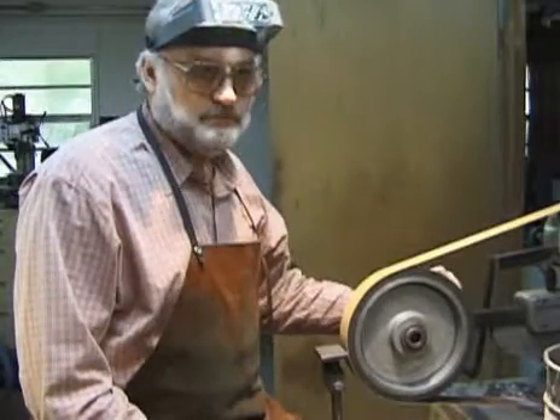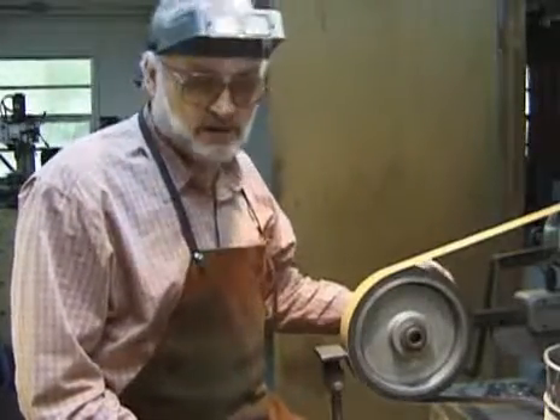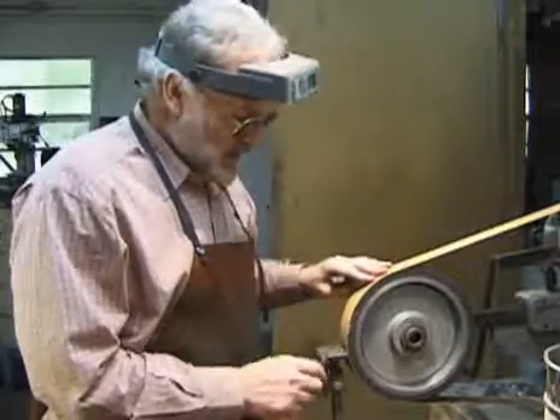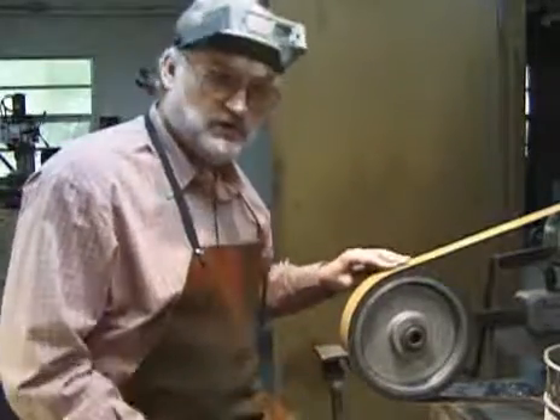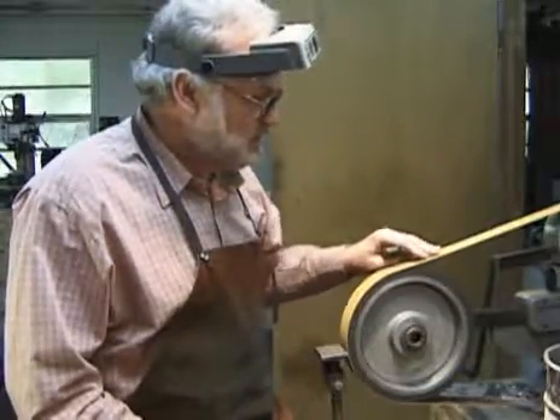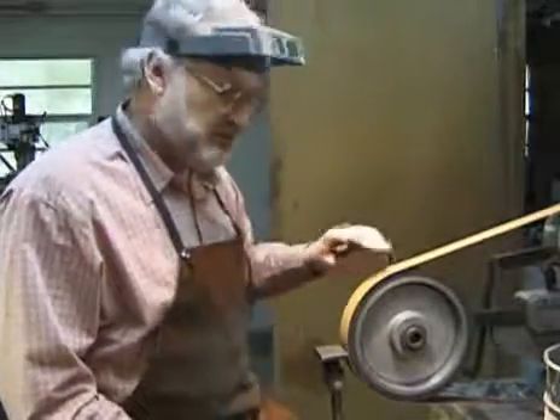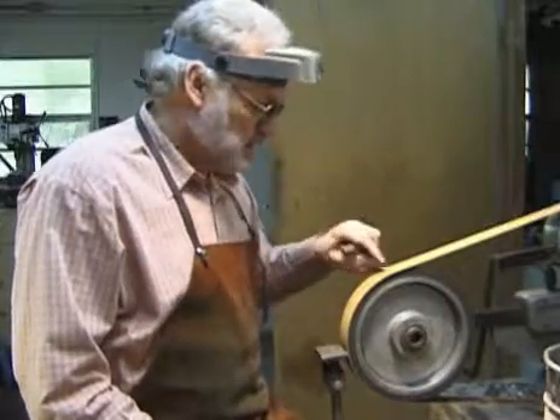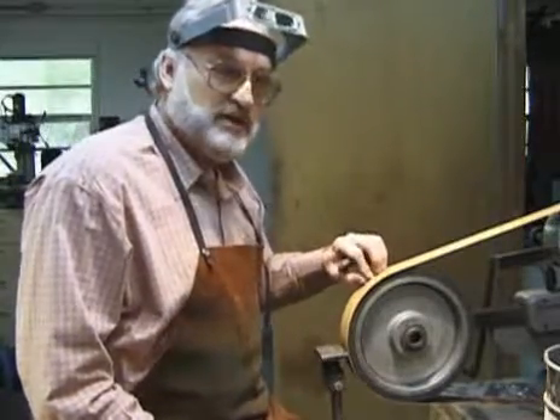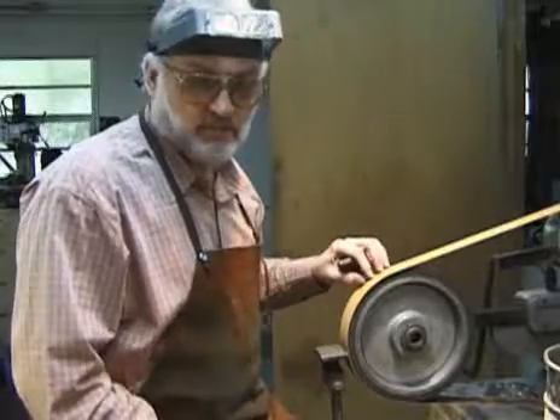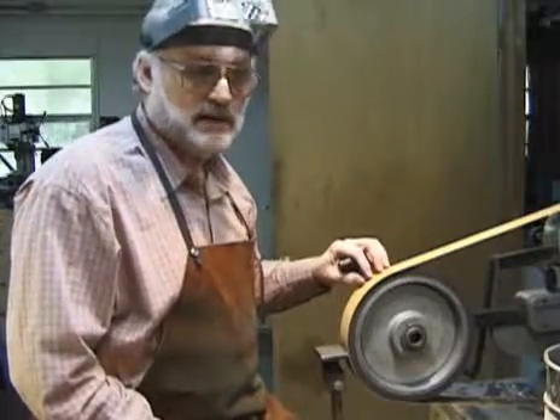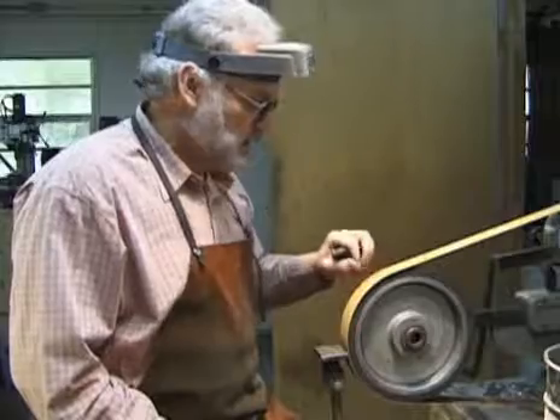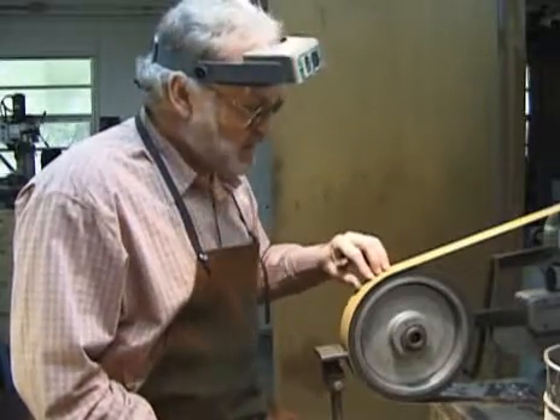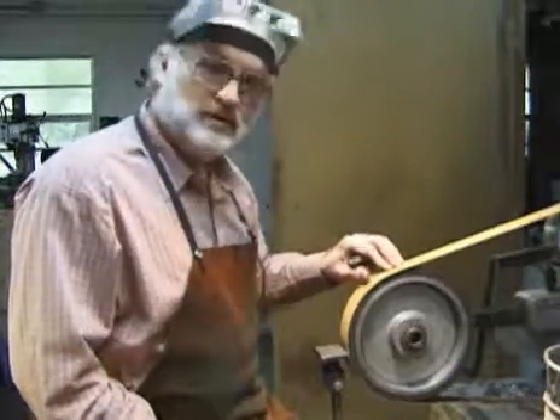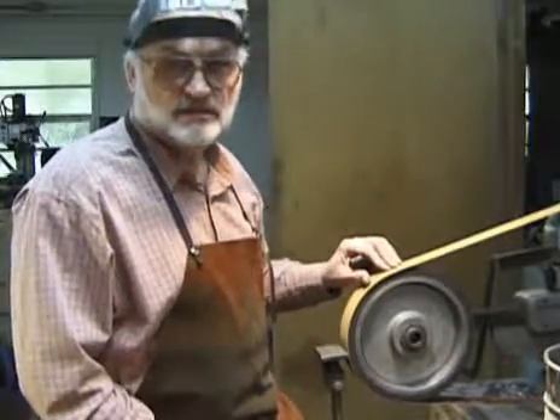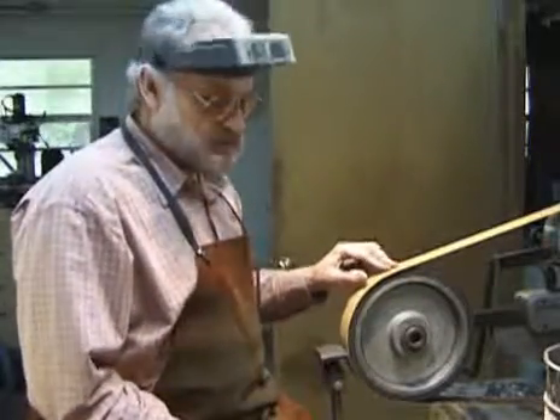When you're getting into your finished grinds on your blades, I'm using a coarse grit here. This is a 60 grit. Actually, it's an 80. No, it's a 60 grit ceramic belt. The benefit of the ceramic, it cuts very, very deep because the grit is so sharp and it doesn't dull like aluminum oxide or silicon carbide. So a 60 grit scratch on a ceramic belt is about like a 36 grit scratch on one of the other belts.